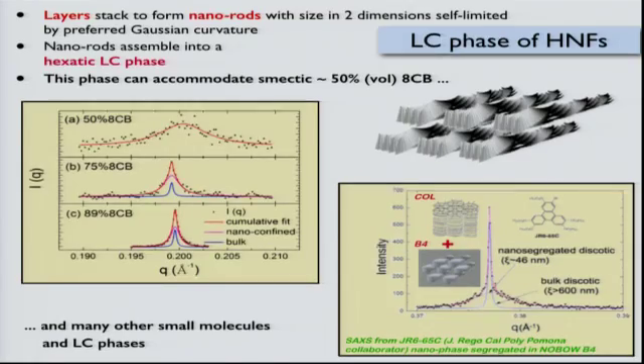So this is 50% by weight, or about 50% by volume, 5CB. Or maybe it's 8CB in the helical nanofilament phase. So you have a 50-50 mixture of these two things. You heat it up until it's isotropic. Then you start cooling, and the helical nanofilaments come out of the 8CB, which is just acting as a solvent. You get slow nucleation, very rapid growth, and you get these large heterochiral domains. And the 8CB, you can cool all the way down to room temperature, and the 8CB has a symmetric peak, and you can see from the peak width at half max from the X-ray scattering from Brookhaven that this thing is nano-confined.